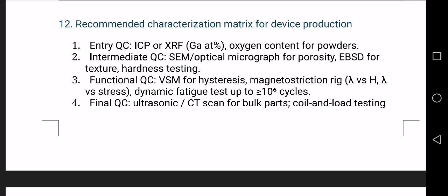Dynamic fatigue testing. This is essential for energy harvesters and sensors. Cyclic loading up to 10^6 cycles or more. Monitor drift in lambda, change in coercivity, and mechanical degradation.